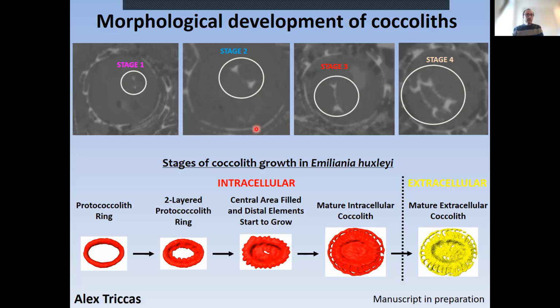And by looking at the cells and the reconstructions, we could pinpoint coccoliths at different stages of formation. I have highlighted here 4 stages from 4 different cells. It's interesting that we have coccoliths being produced at the same time on Emiliania. And this is the reconstruction from 4 different coccoliths from each of these stages that are representative of what we observed. And we can see it very much matches what is in the literature.